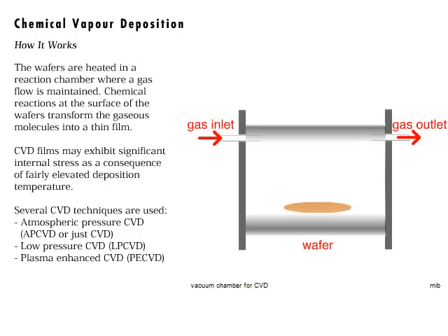In general, AP-CVD produces thin films with a poor step coverage, while LP-CVD offers very good uniformity, step coverage, and quality of the films. PE-CVD provides much more process parameters to control the characteristics of the deposited films, in particular stress. The trend in PE-CVD goes towards the deposition at room temperature with high-density, inductive-coupled plasmas known as ICP.